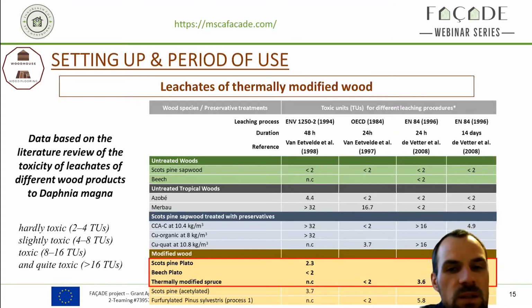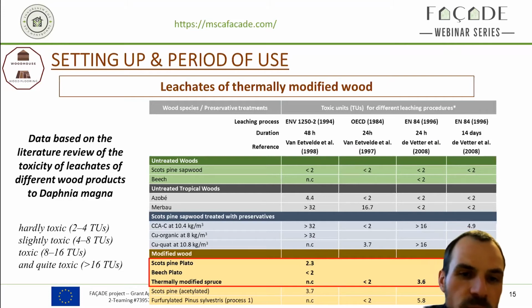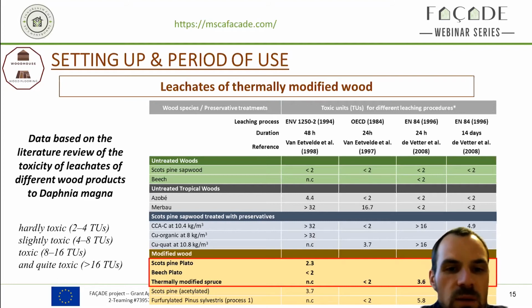In the second one, during its service life, the modified wood material can be submitted to natural leaching and aging, often generating some chemical products with potential toxic activity. For example, I put on this slide a table presenting several results about toxicity activities of water leachate from thermally modified wood against the Daphnia magna organism after different laboratory leaching processes. According to these comparative results, it appears that water leachates from thermally modified wood are less toxic than those of tropical wood or chemically modified wood.